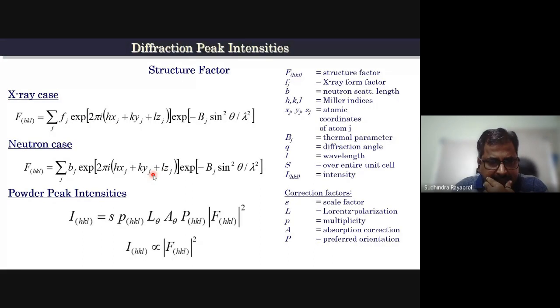Okay, as far as powder diffraction is concerned, X-rays and neutrons are almost identical in terms of refinement also, but the difference comes in this equation. This is the equation for the structure factor, which is the most important quantity in the generation of the calculated diffraction pattern. So in case of X-rays, we have what is called the X-ray scattering structure factor, which depends upon the X-ray form factors.